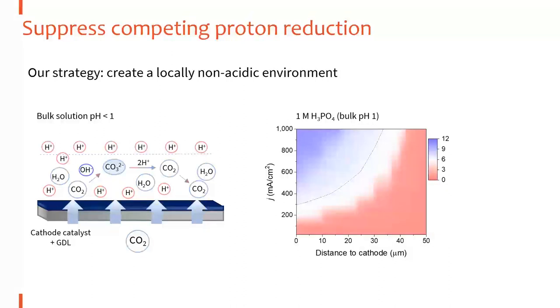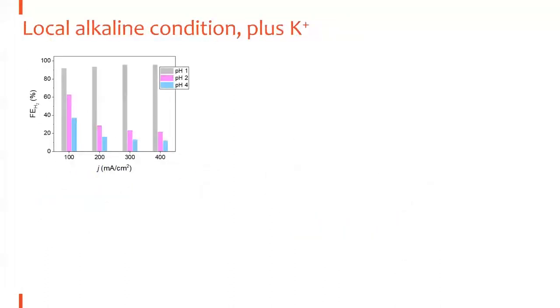So once we form bicarbonate here, once it diffuses across this line, it will encounter a lot of protons and low pH, so it will be converted back into CO2 molecules, so that it can reach back to the surface for further reaction. Even if we generate carbonate, it only happens locally around the cathode, so we have a chance to convert the carbonate back into CO2.